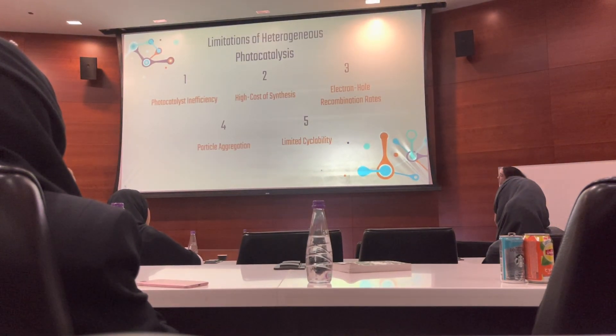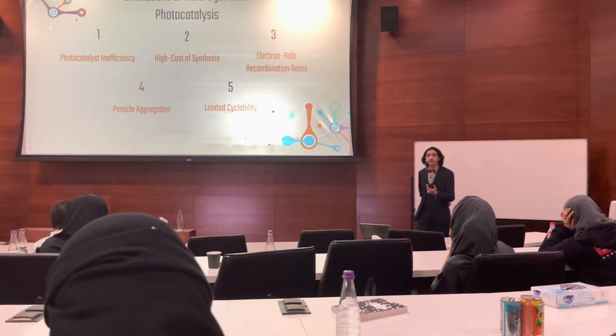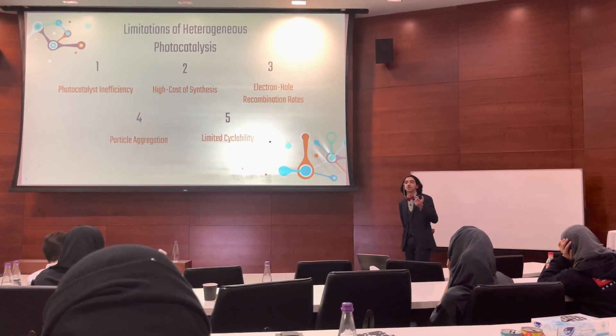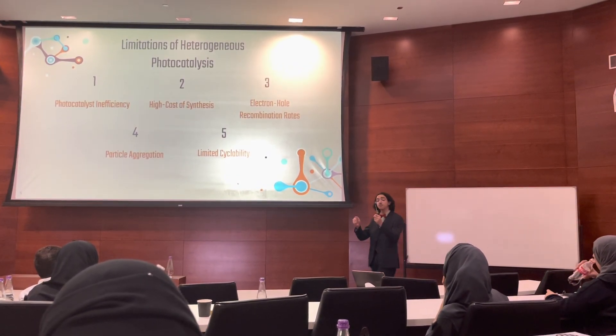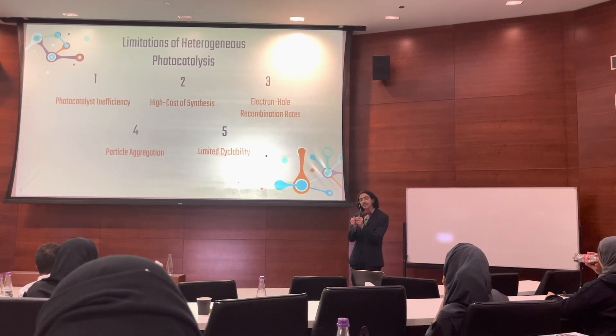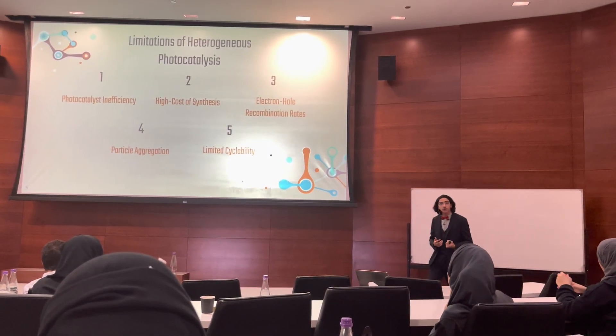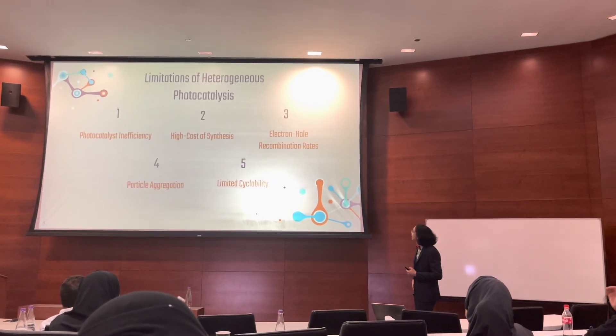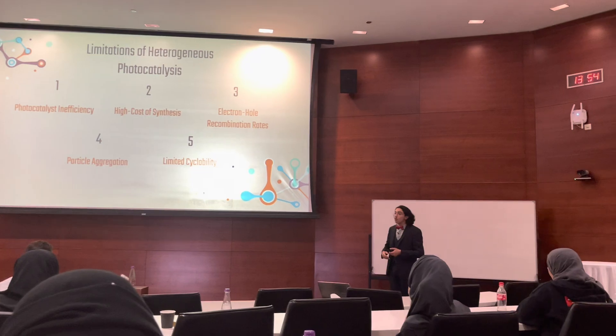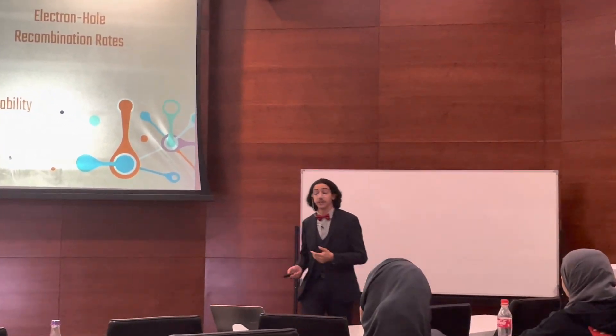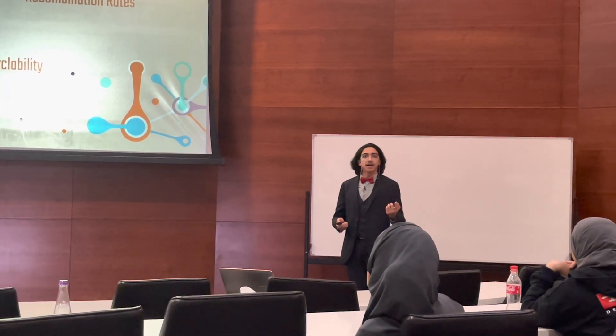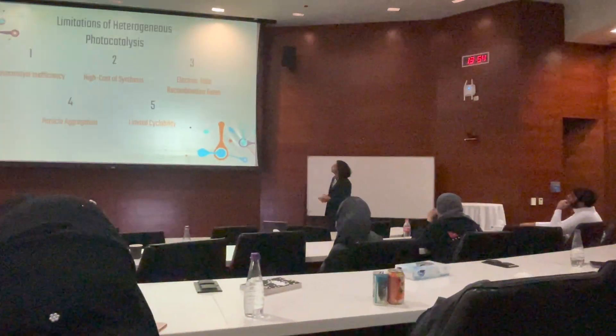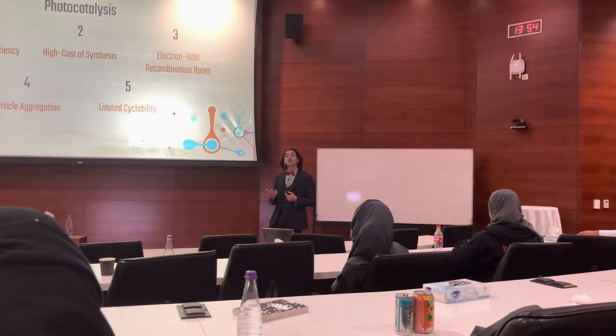Another issue is particle aggregation. Because we're dealing with heterogeneous catalysts that exist in a different phase than the reactants — my metal oxide phase is a solid powder — while the reaction happens in water, a liquid medium, these particles tend to aggregate, causing loss of potential surface area and a very low overall rate of reaction. Finally, there's cyclability: if a material only works once after all that synthesis and cost, that's a serious problem. These are all issues we're trying to mitigate.